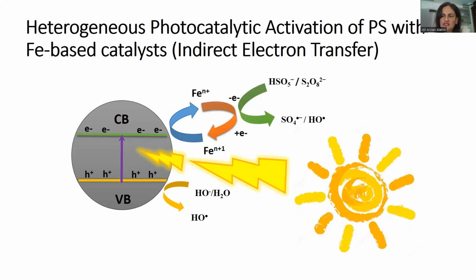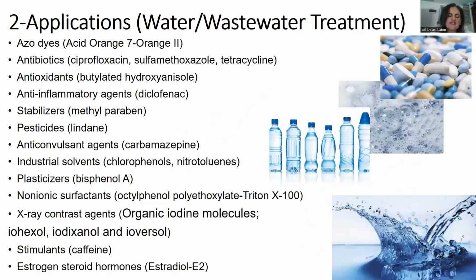So the involvement of iron as an intermediate: iron can be reduced by the conduction band electron, so an indirect electron transfer, and it is reacting with the PDS in a Fenton-like reaction. That's one effect of this indirect electron transfer. And then we also have hole oxidation and formation of the other oxidizing agents.